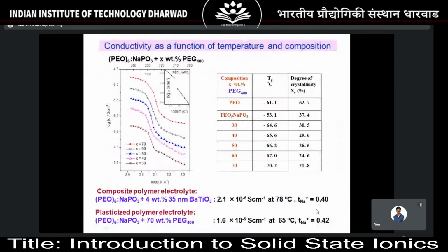So here you would have noticed 2 things. And I told you in the beginning as well, how do you recognize that a material is an ionic conductor? By means of its transport number. The transport number is of 2 types: one is the ionic transport number and the other is the electronic transport number. Electronic transport number means the ratio of electronic conductivity to total conductivity. It will be very, very low. Whereas the ionic transference number is the ratio of ionic conductivity to total conductivity, and it will be tending to 1.